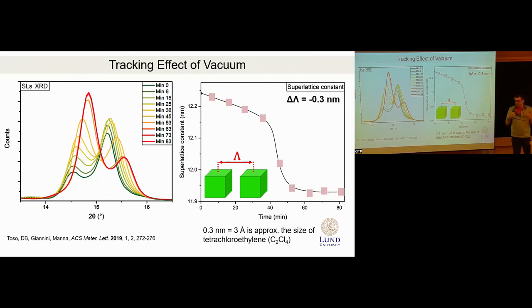Okay. If you do a peak fitting analysis, does the peak breadth change as time goes on? Say again? Does the peak breadth change? So imagine if everything is uniform throughout and you're drying asymmetrically, so the top layers lose it first, whereas the bottom layers, that would change. That could give rise to weird non-linear effects. We could also expect a broadening of the peak. Yeah, we haven't looked at that, because at the time, we were only able to do analysis just by looking at this lambda. So now we could also do more detailed analysis and determine, for instance, disorder also. If we go back and reanalyze this data, yes, I think we might see, for instance, that the top layers would go closer, perhaps more ordered, while the bottom will remain still wet.